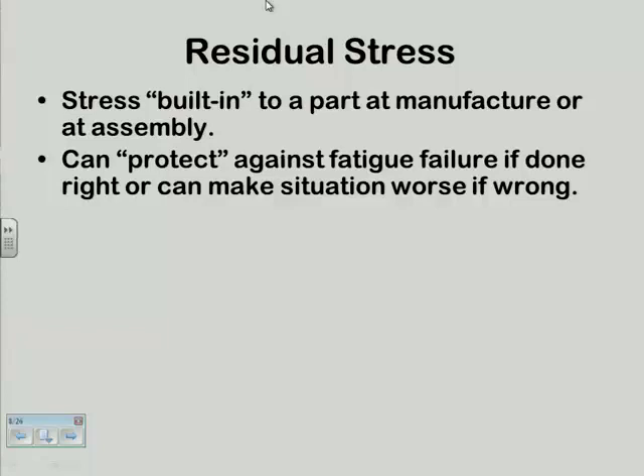Fatigue failures are tensile in nature — that's well proven. Tensile stress is the culprit. Compressive stress does not fatigue-fail things because it closes the cracks. So if I can build in compressive stresses, it's like a safety valve. If I force compressive stress into this part and then start to put tensile stress on it, I have to bring the tensile stress up from the compressive regime before it really becomes tensile — the compressive is subtracting from it. In essence, I'm pushing down the threshold by building in compressive stress.